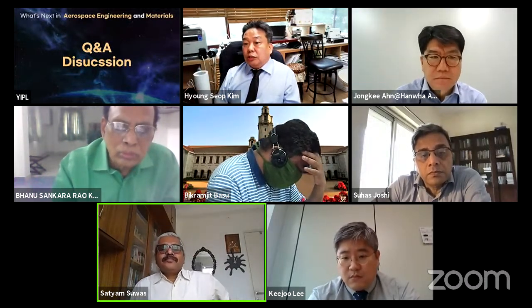That's what I'm saying. And I want to comment on this surface roughness and surface residual porosity problem. As Professor Suhas mentioned, surface treatment is a very good way to remove the residual stress and extend the fatigue life. He used SMAT, surface nanocrystallization. It can refine the surface grain to nanocrystalline, and in addition, surface compressive stress is highly generated. It's a very good way to avoid surface fracture or something like that.